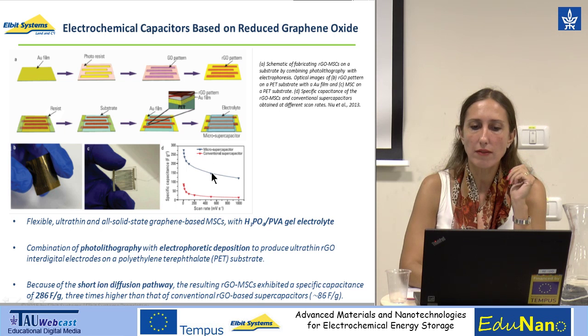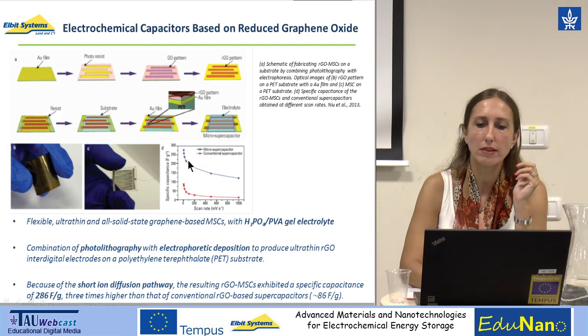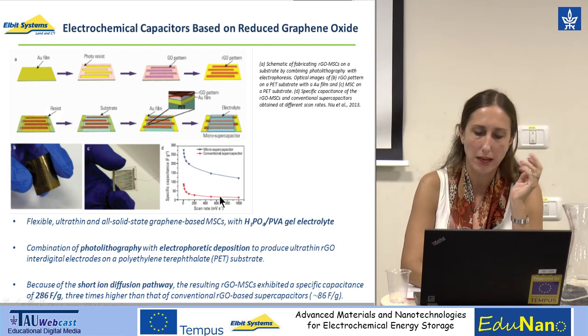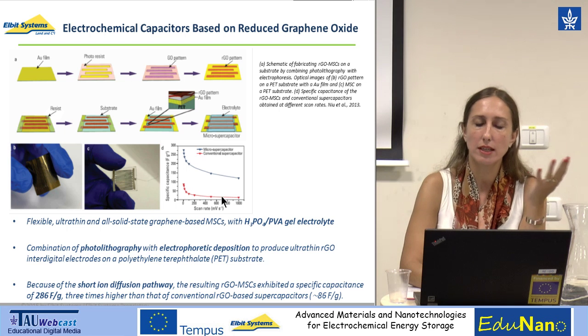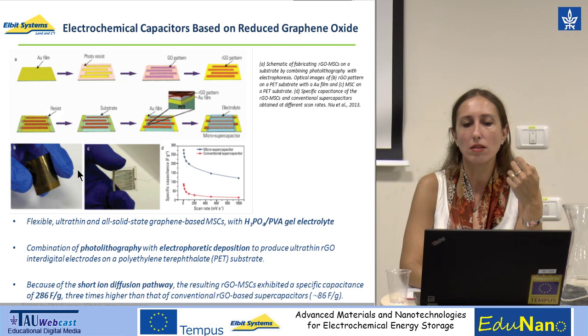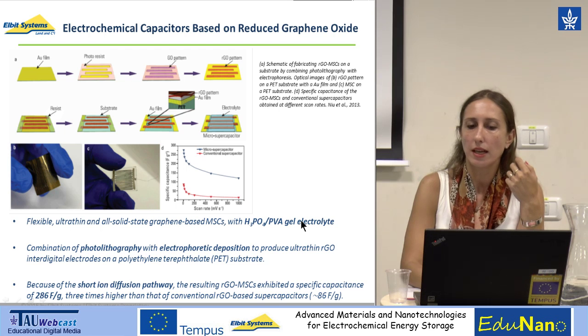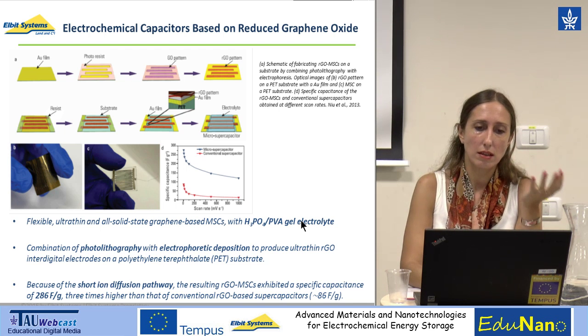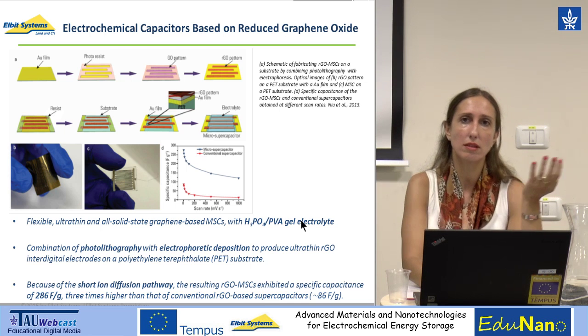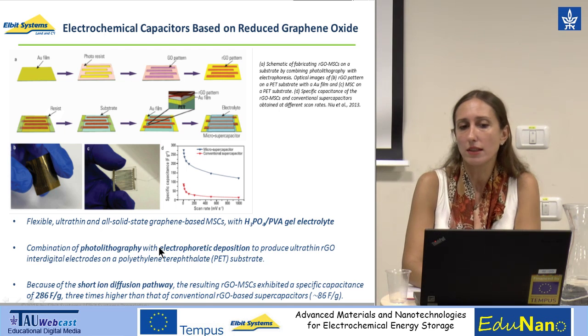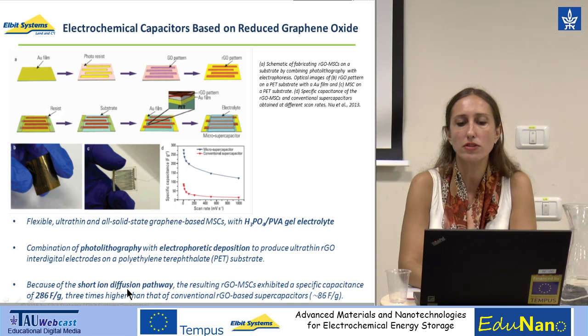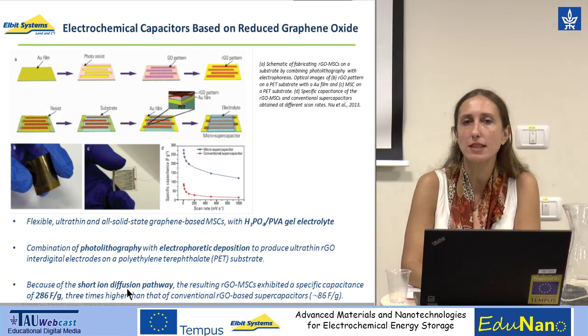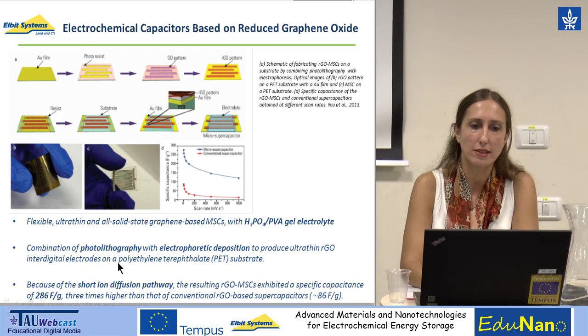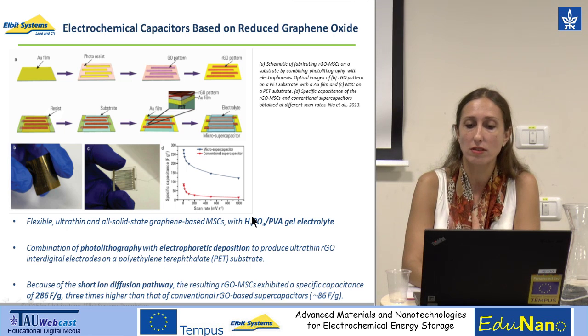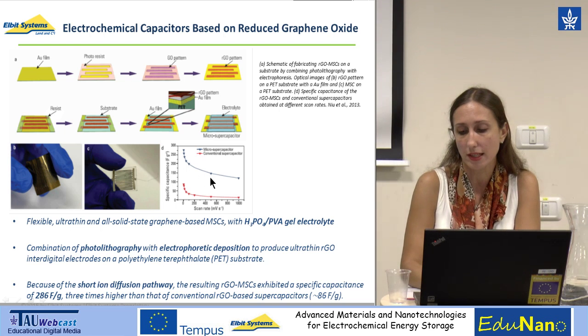And the graph over here shows the specific capacitance versus the scan rate of these RGO MSCs, shown here in blue, in comparison to conventional supercapacitors here in red. So one can see that in the end of the day, here you attain flexible, ultra-thin, and all solid-state graphene-based MSCs with this phosphoric PVA gel electrolyte. The fabrication methods are the methods known in the microfabrication of semiconductors, photolithography, electrophoretic deposition. These are well-known techniques, and because of the short ion diffusion pathway, the resulting RGO MSCs exhibited a high specific capacitance of 286 farad per gram, which is 3 times higher than that of conventional RGO-based supercapacitors with approximately 86 farad per gram.